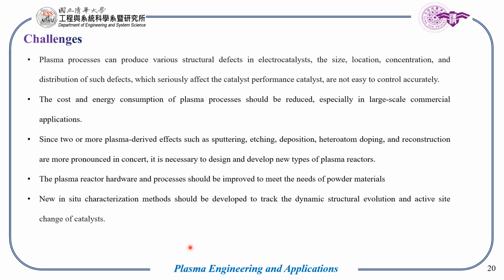The current problems being faced in plasma technology are, first, that the plasma produces various structural defects, and the size, location, concentration and distribution of such defects, which seriously affect the catalyst performance, are not easy to control. When we use any plasma source to create surface defects on an electrocatalyst, it cannot be controlled. We can just control the amount of plasma that we are applying, but we cannot control the amount of activation sites created. It may create a large amount of activation sites, it may create a small amount, or it may also destroy the whole property of the electrocatalyst.